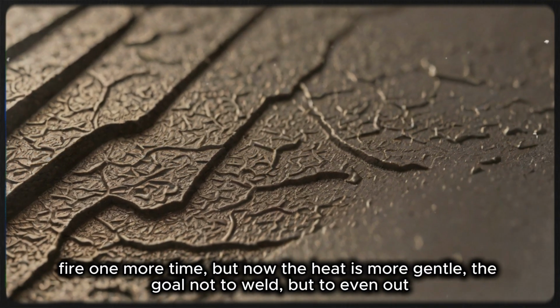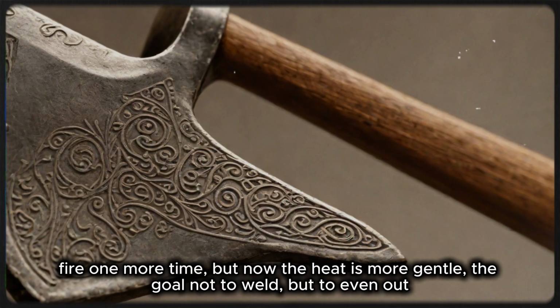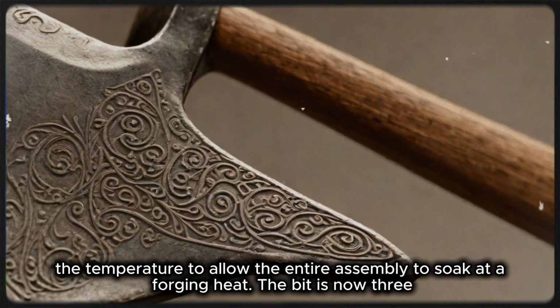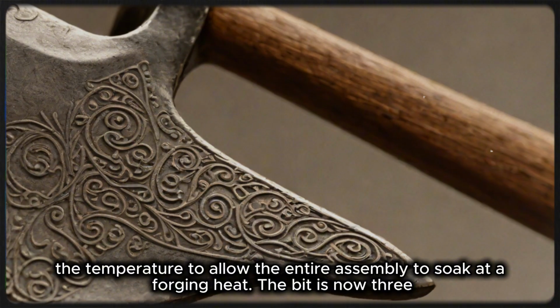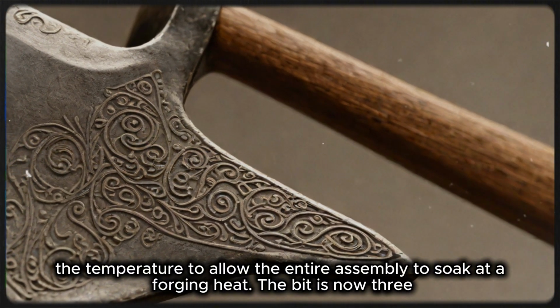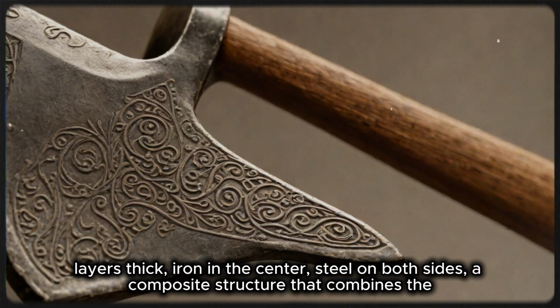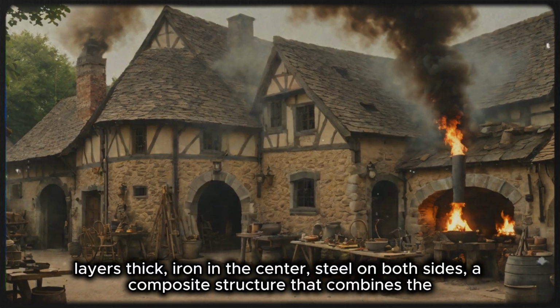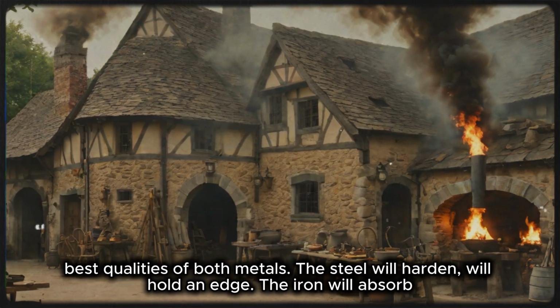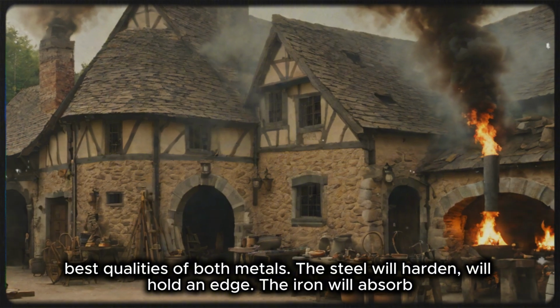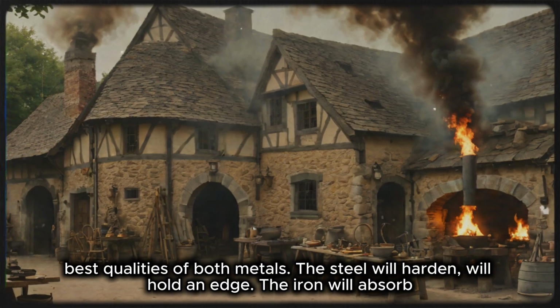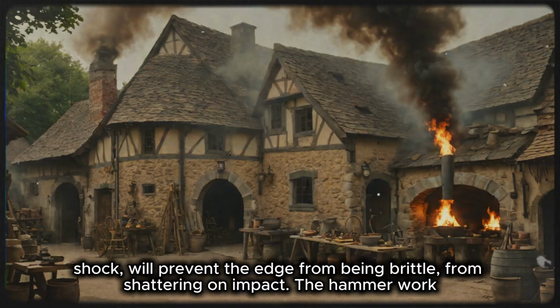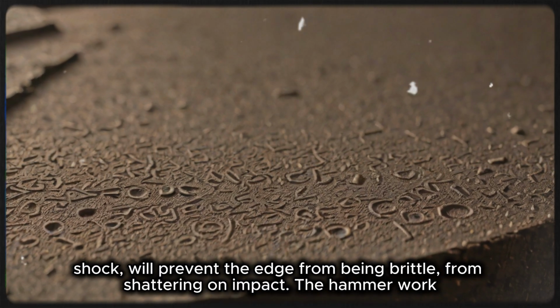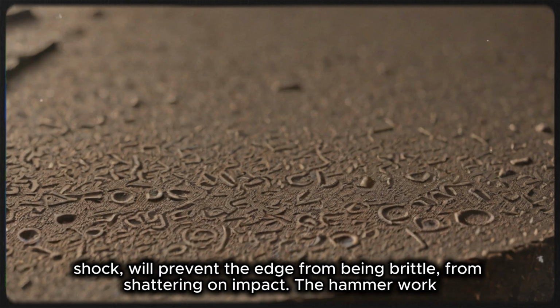But now the heat is more gentle, the goal not to weld, but to even out the temperature, to allow the entire assembly to soak at a forging heat. The bit is now 3 layers thick, iron in the center, steel on both sides, a composite structure that combines the best qualities of both metals. The steel will harden, will hold an edge. The iron will absorb shock, will prevent the edge from being brittle, from shattering on impact.